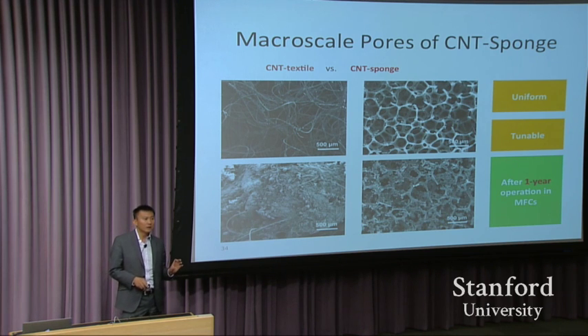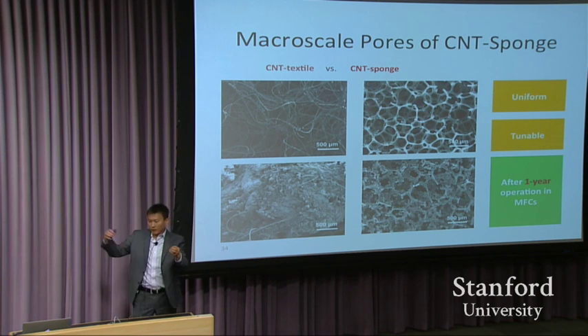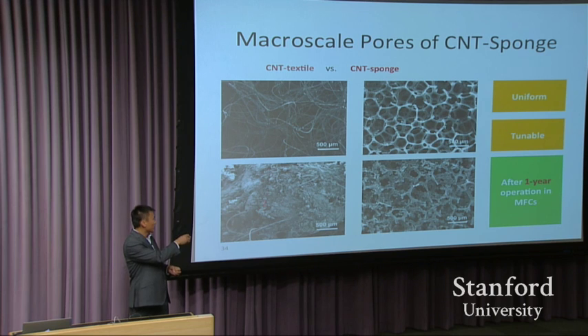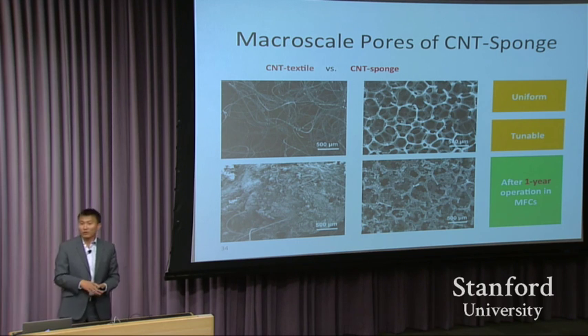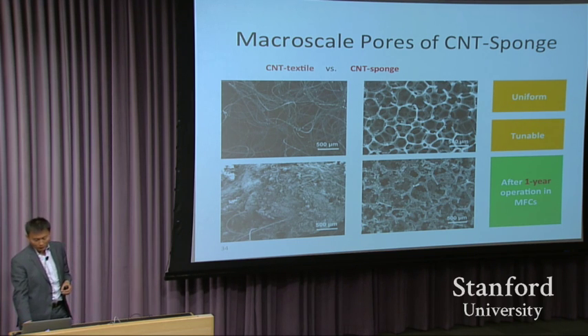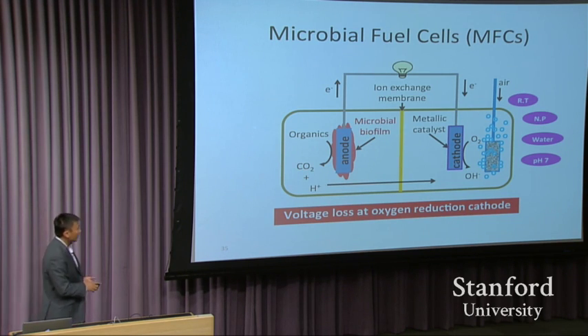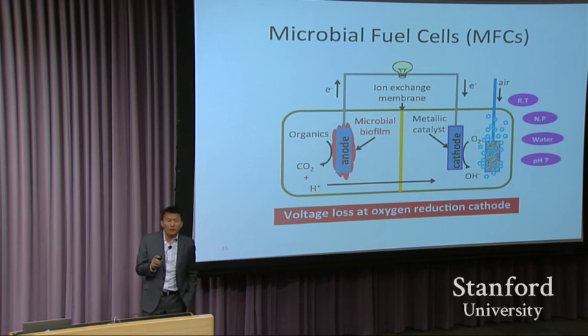This is important. That's because these microbes need to consume organics, right? The wastewater is coming in with this organics. If this blocks all the pores, then the microbes inside this electrode don't have nutrition anymore. They might die. That's number one. The second one is the concentration of organics becomes lower, and they don't do that much job. Only the top surface can do the job. So this is a better electrode. We actually show that using this sponge. This is much better.